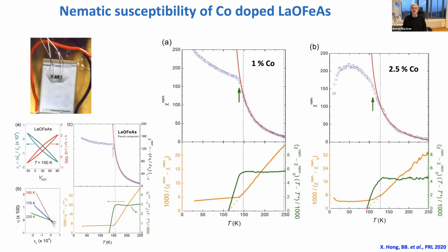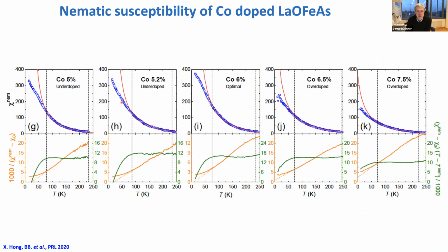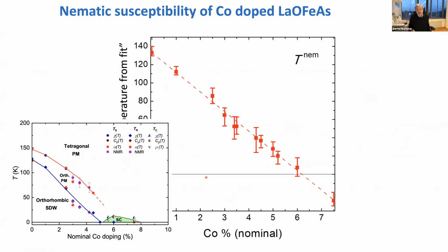And then you can follow this behavior up to very high concentrations. So this is underdoped, and we go to overdoped samples. When you look at the Curie-Weiss temperatures, you see that it first is positive, and it crosses zero just at optimal doping, which is the best superconductor we have in these systems. And then it becomes negative for the overdoped compound. So it's very easy to identify the optimal doping from the normal-state strain derivative of the resistivity. This is the corresponding diagram of the nematic susceptibility, this characteristic Curie-Weiss temperature as a function of doping. You see the crossing here at 6%, just where we have optimal doping. So in some sense, you continue this line even though the structural phase transition, or the real 3D order, disappears. Just looking at the characteristic energy scale, we follow this line, and it hits exactly zero at optimal doping.